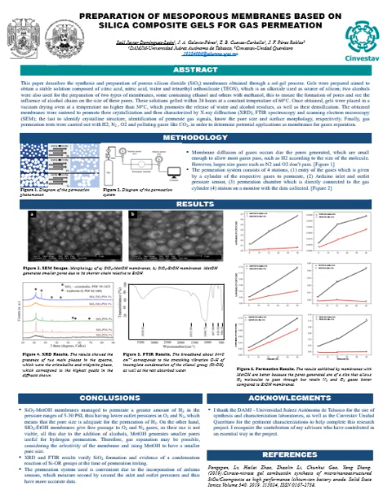The findings revealed that there were two primary phases present in the spectra, namely the cristobalite and tridymite phases. These phases align with the most prominent peaks observed in the diffraction patterns. The FTIR spectrum of silicon dioxide is depicted in Figure 5. It's evident that the broad band around 3440 inverse centimeters corresponds to the oxygen-hydrogen stretching vibration resulting from the condensation of silanol groups, as well as the presence of adsorbed water.